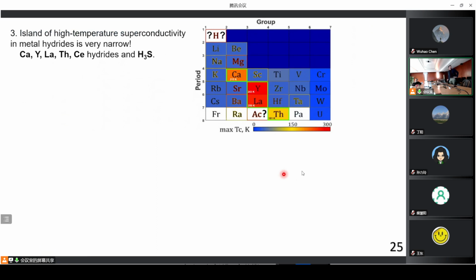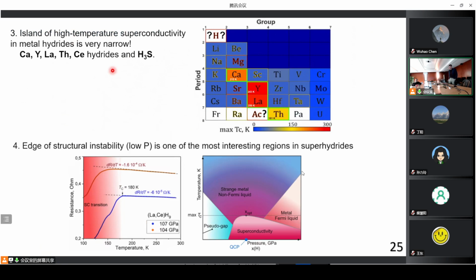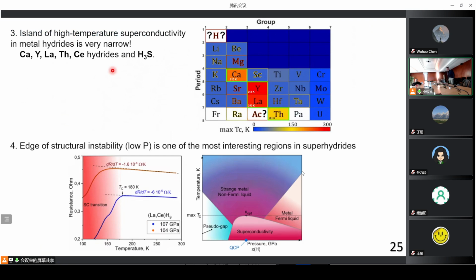I would like to again say and repeat that the island of high temperature superconductivity is extremely narrow. We have only a very narrow choice, about 4 or 5 elements, for how to construct ternary systems. We can use calcium, yttrium, lanthanum, thorium, maybe actinium, but it's quite complex, and H3S and maybe cerium hydrides. That's all that we have. Actually, high temperature superconductivity in polyhydrides is a very rare phenomenon.